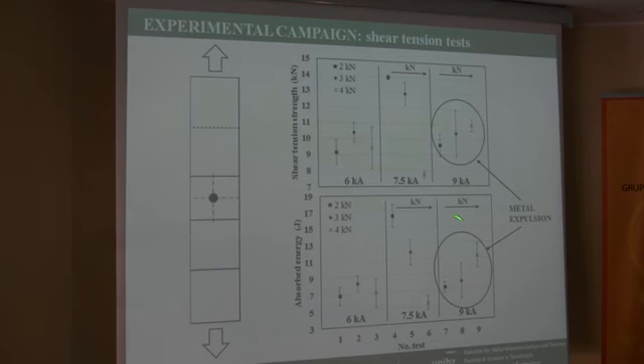If you look at this picture, you can see the trend of absorbed energy obtained during the tests, and you can see that we have more or less a similar trend to the shear tension strength values. Also in this case, the metal expulsion defines a loss of absorbed energy in these samples.